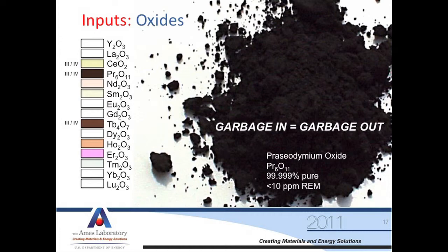Let's get back to the making of the rare earths. We're going to comment on where we start — it really starts with the inputs. There are two ways to make it: you can either start with high purity materials and keep it pure, or you can find some slick way to get your impurities out. This is a picture of praseodymium oxide. Rare earth oxides are very colorful; they come in whites, purples, and yellows. Praseodymium oxide looks black. This is very high purity — five nines, as we call it — meaning there's only 10 parts per million impurity in it. For every million atoms, 10 of them are something other than what we want. That's pretty darn pure, and it's expensive because it takes a lot of effort to get there. Garbage in, garbage out: if we start with a lot of impurities, we're not going to get them all out. So if we want to make the highest purity rare earth, we've got to start with the highest purity oxide.